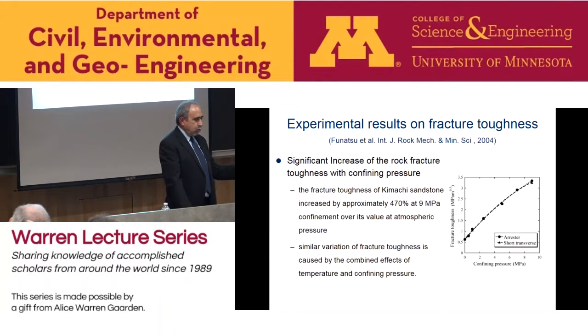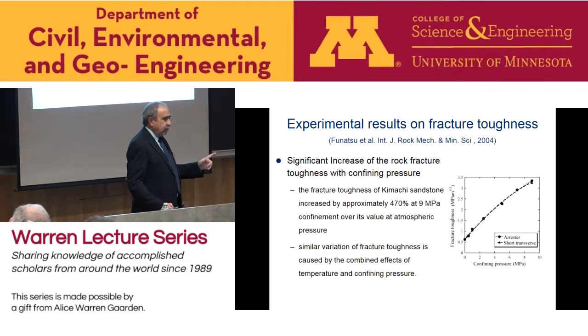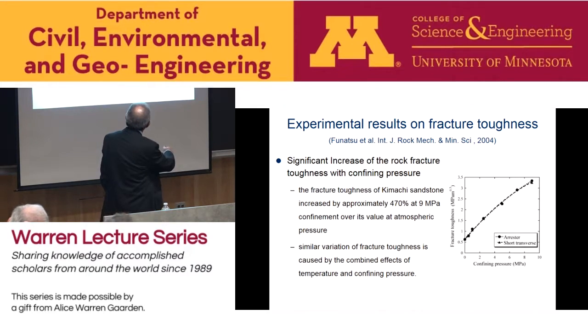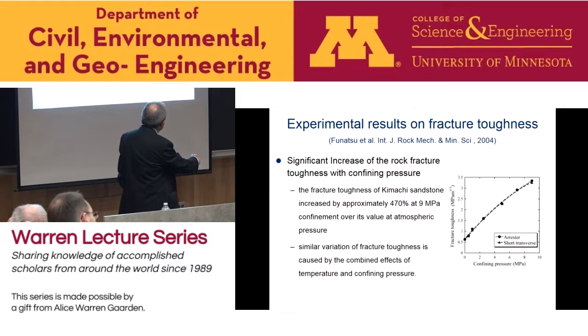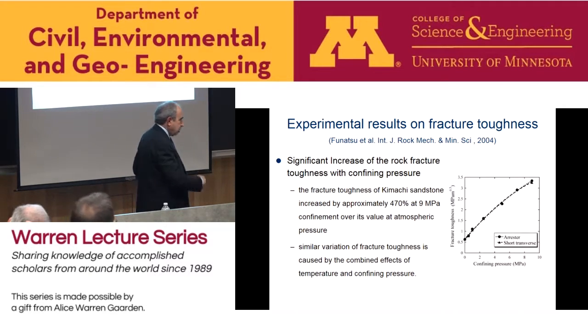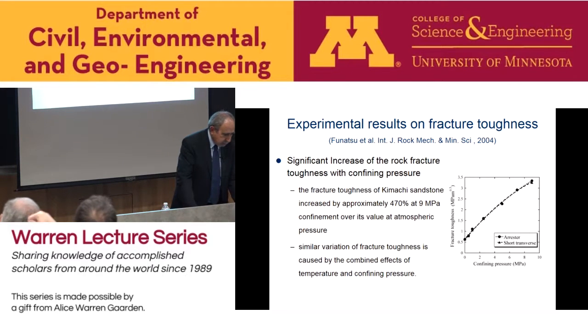Just to show some experimental results on fracture toughness, how it varies with confining pressure. I found this paper, Funatsu, it's from Japan, published in 2004, and basically they show that the fracture toughness increases with the confining pressure, in this case by 5 times, but as you can see here, we haven't reached a limit value yet. If it was possible to continue, it would increase even further.